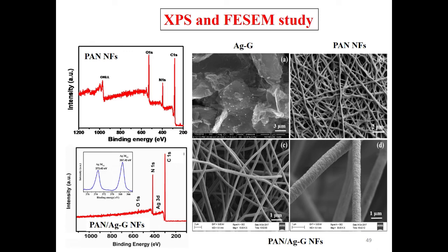This is the XPS study and scanning electron microscopy study of this material. The binding energy shifts very effectively, with convoluted and deconvoluted spectra of silver 3d5/2 and silver 3d3/2 at 367.45 electron volts and 373.43 electron volts. That is the binding energy of this material. This image shows a very highly porous structure, with very effective decoration of silver nanoparticles over the surface of the PAN nanofibers with a high porosity.